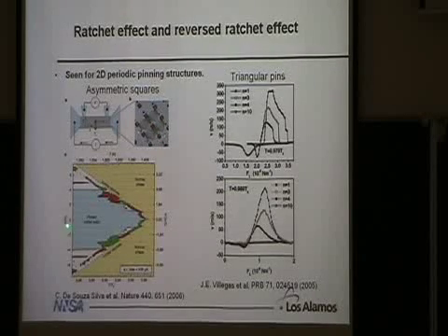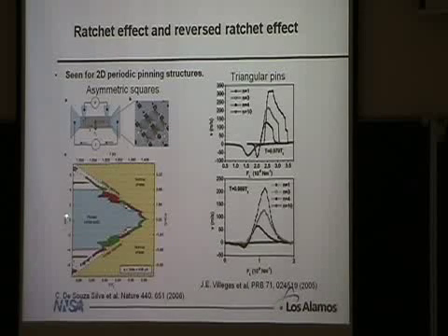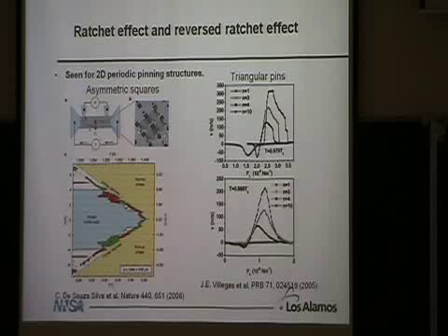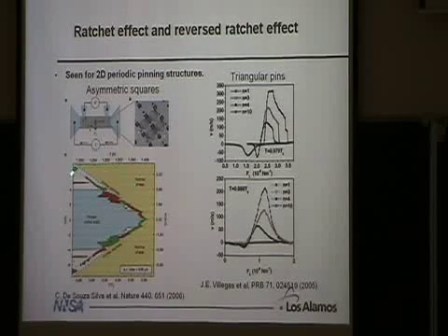What they found is that as they change the magnetic field, over the temperature in which they're operating this system, the direction of the ratchet would change. So red here would be a forward ratchet that you would expect. Green would be switching to the backward ratchet. Red is forward again. Green is backward again. So they see a bunch of reversals as they're changing the magnetic field. They basically observe this, but they don't really describe why these reversals are happening.